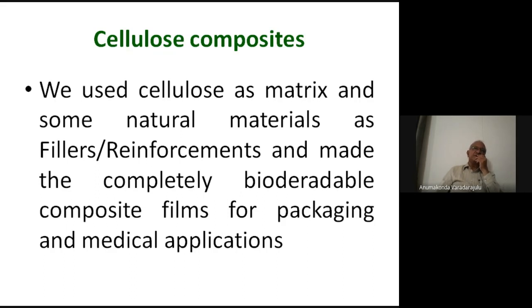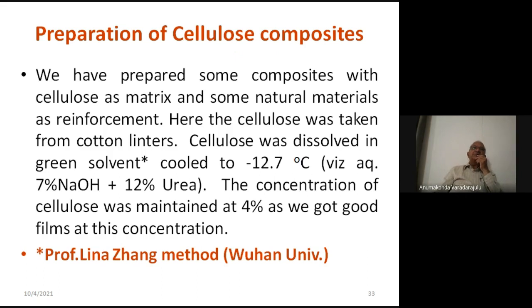And cellulose is one such biopolymer, that is the cotton. And then we used cellulose as a matrix and some natural materials as fillers or reinforcements, and made completely biodegradable composite films. But processing of the cellulose is a very big problem, because it degrades before its melting point. The only way is you can make it by solution method. For that we have to dissolve the cellulose. But cellulose dissolution is a very difficult problem.